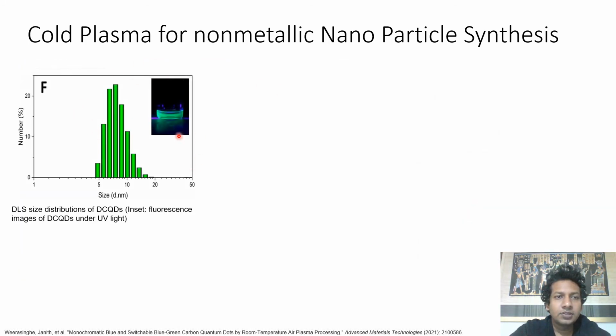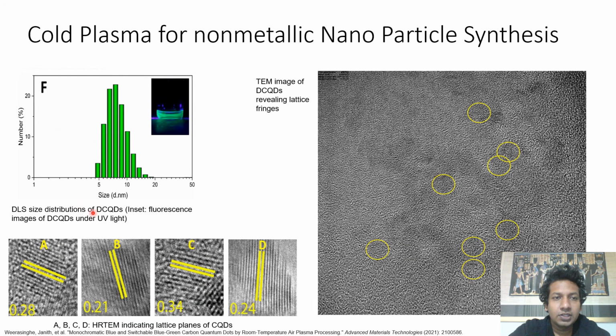This is how the synthesized carbon quantum dots look under UV light. The maximum emission peak for green is at 515 nanometers under the excitation of 400 nanometers. DLS data reveal the mean hydrodynamic diameter of 7.5 nanometers. According to the TEM images obtained, carbon quantum dots are spherical in shape and uniformly dispersed from each other. The average size is about 2.4 nanometers.